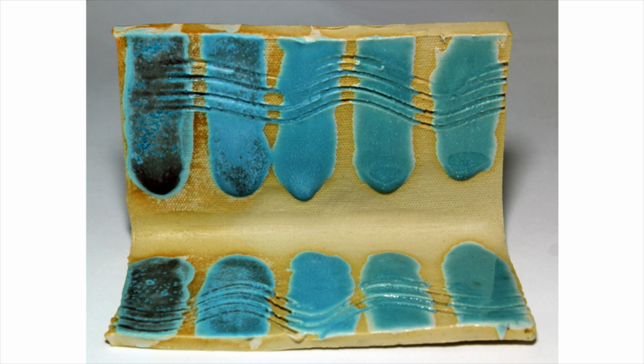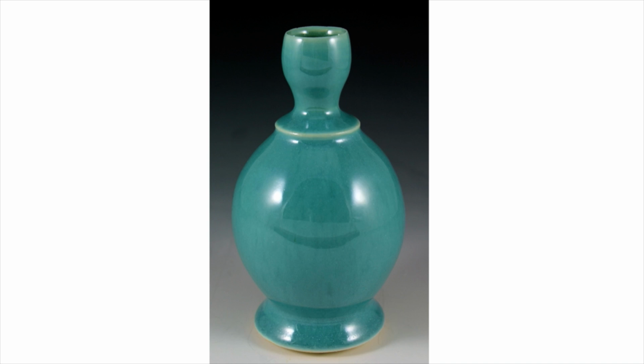And eventually a glossy surface. Take out the silica and then add it back into the glaze in 10 to 20% increments. Note how the glaze changed from a matte glaze to a glossy glaze with these additions of silica, which is the glass former in our glazes. I chose the last stripe, mixed up that recipe, and glazed this bottle.